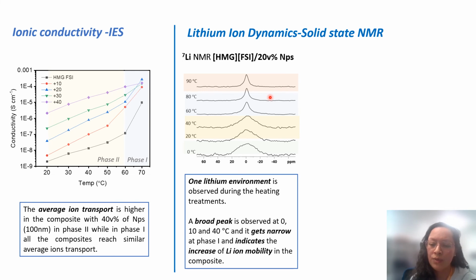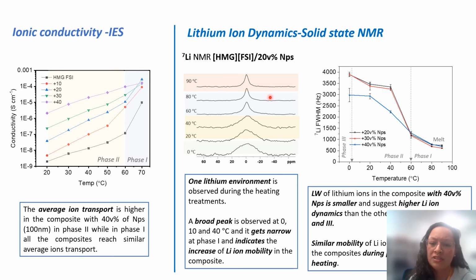We measured the line width of these peaks, and we also performed these experiments in the composites with 30 and 40 volume%. We found that the composite with 40 volume% has the smallest line width, which means that in these materials the lithium ions had higher ion mobility. For that reason, we think that this is the best composite of this set of materials studied.